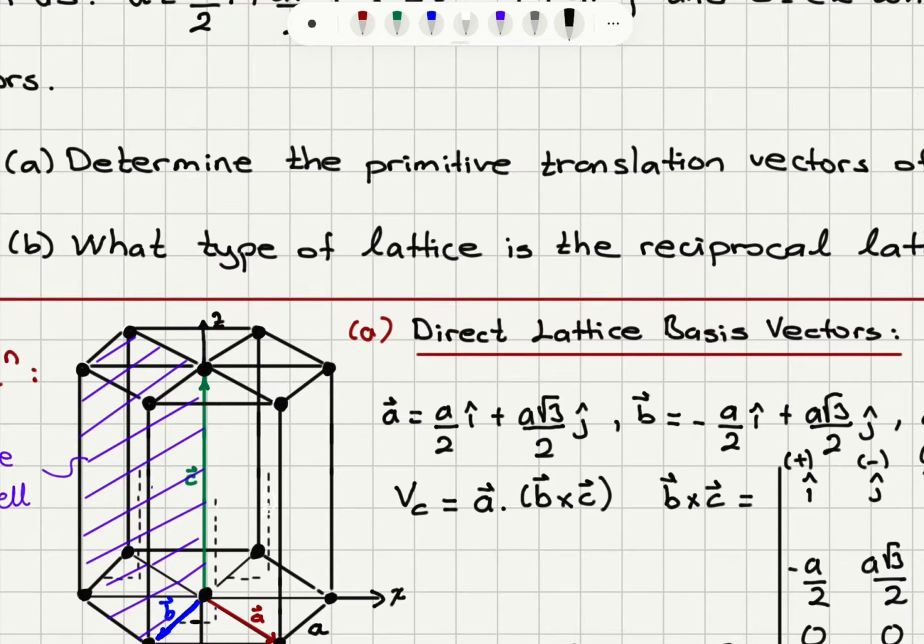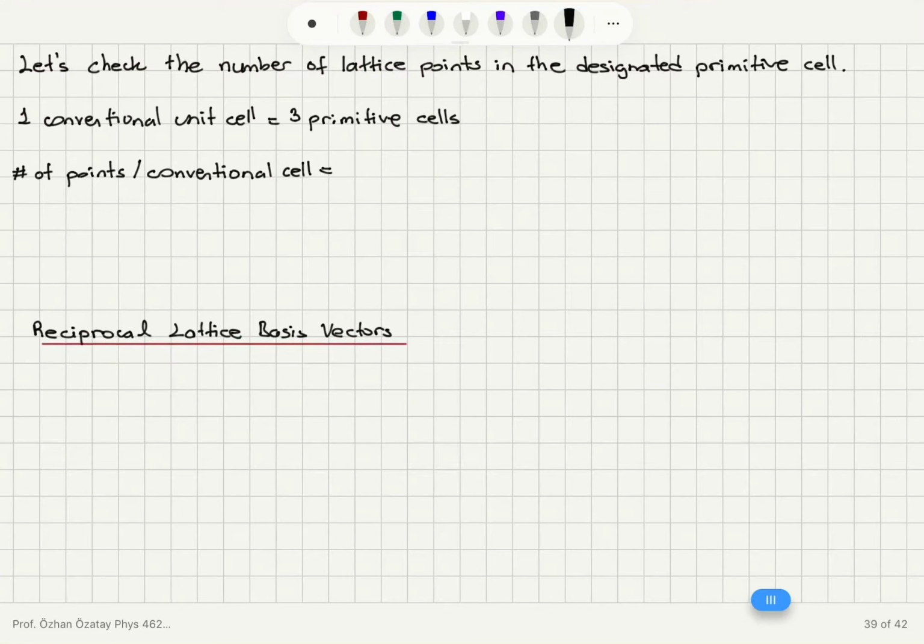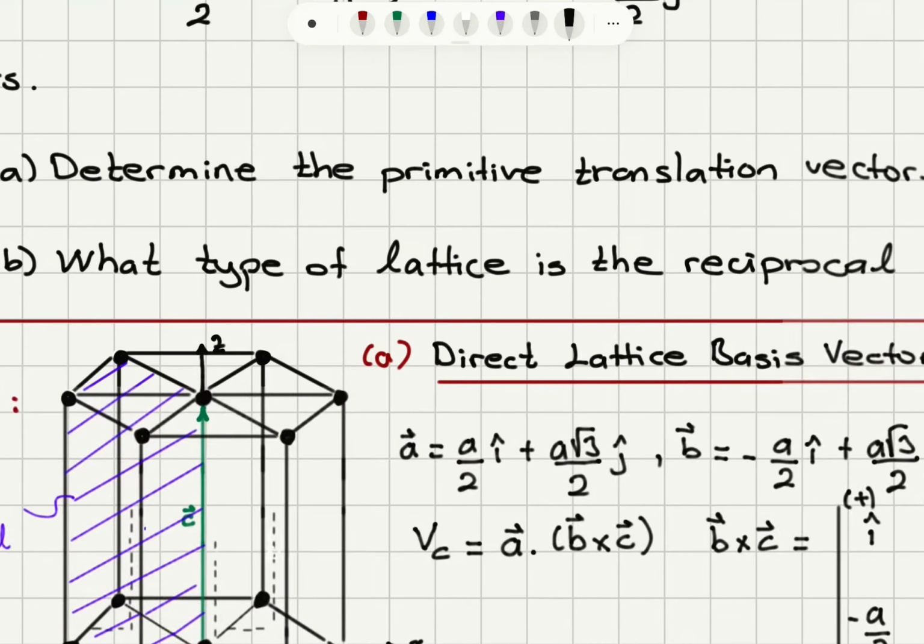So with that, I will do the same thing for these 6 lattice points here. So I will have 1/3 from the 120 degrees divided by 360, 1/2 from top and bottom unit cells, and there are 6 lattice points. And this is for the top plane, but I have also the bottom plane, so 1/3, 1/2, 6 from the bottom plane, and then I have the center atoms, or the center lattice points.